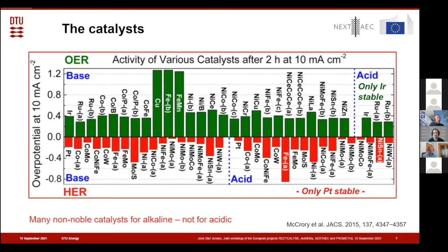For the electrodes and catalysts, there is a much larger variety of materials that can be used in the alkaline system. In the acidic system, the PEM system is acidic. It is practically only iridium so far, perhaps with some ruthenium as well, but ruthenium alone dissolves. So it's platinum and iridium, and despite years of trying, we have not found a solution to that.